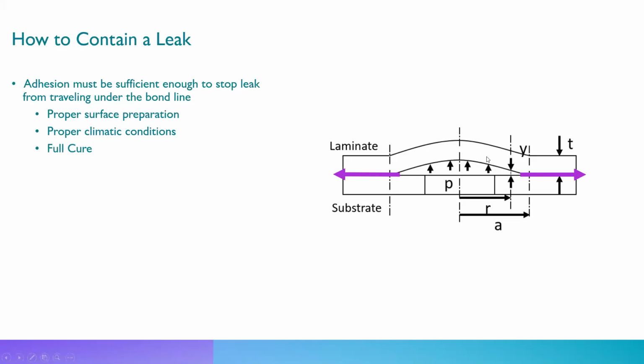So for high pressure leaks, we're going to want the best type of surface prep, which is abrasive blasting. We do have minimal surface preparation products in which if you can't abrasive blast, we can get it done with a lesser prep. But basically, the higher the pressure, the better you want your surface preparation to be.